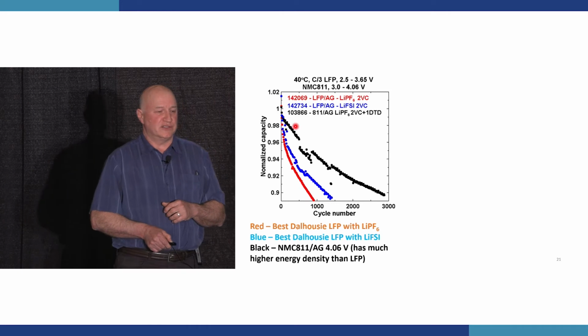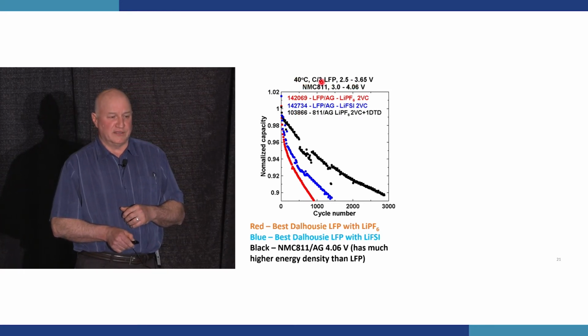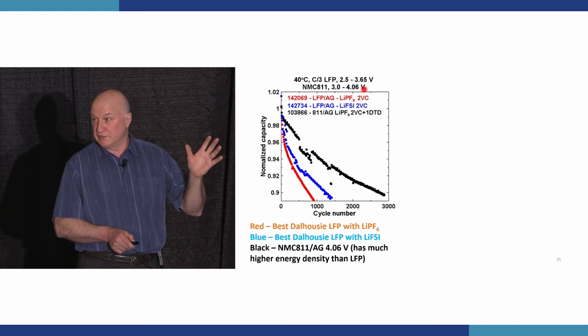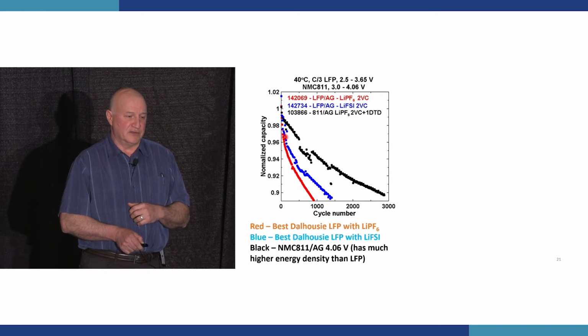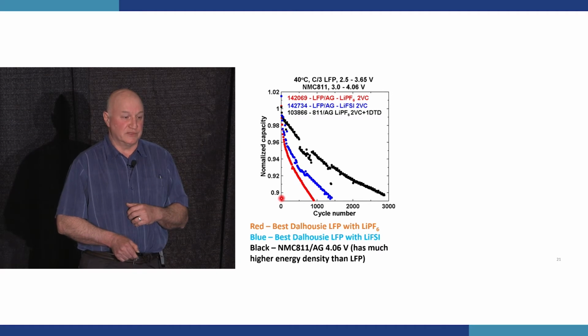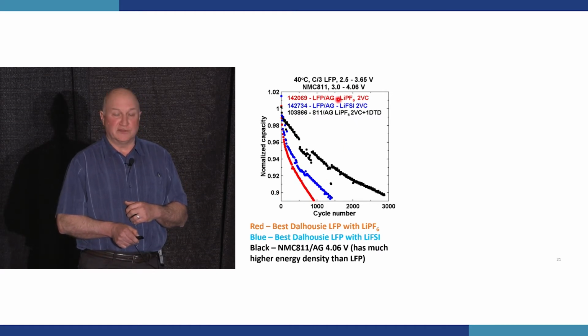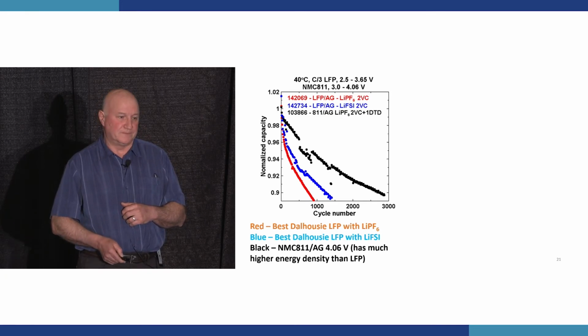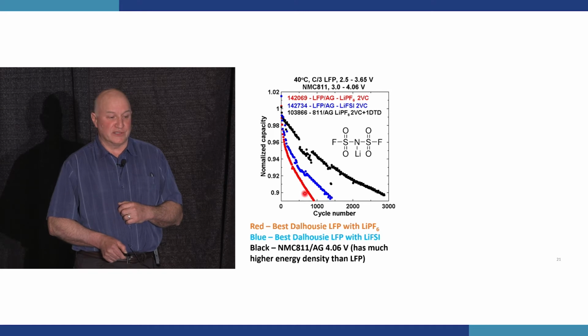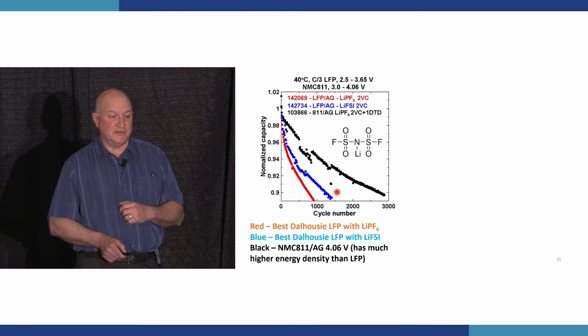So here on the left side, I show testing results again at 40 degrees centigrade for LFP cells running at a 3-hour charge and 3-hour discharge, and also for NMC 811 cells going to this 4.06 volts, avoiding the volume change. So in red, we have lithium iron phosphate graphite cells, 1,000 cycles at 40 degrees C to reach 90%. And those have the normal electrolyte salt, lithium hexafluorophosphate, that we all use in lithium ion batteries. But if you change the electrolyte salt to this lithium bisfluorosulfonylimide, LiFSI, as it's called, you follow the blue curve, and you get about 50% more charge-discharge cycles to 90%. It's much better. But look, when you compare it to the NMC 811, it's worse by about a factor of 2, okay? So don't think that LFP is super good.